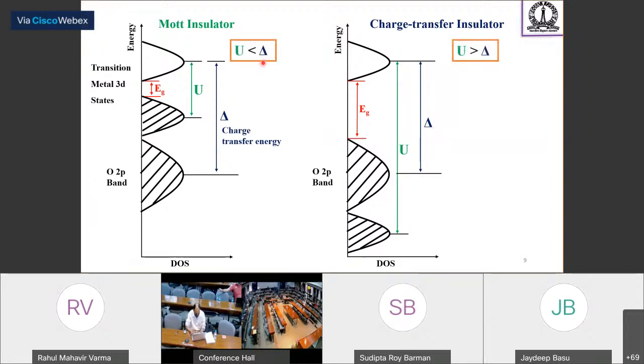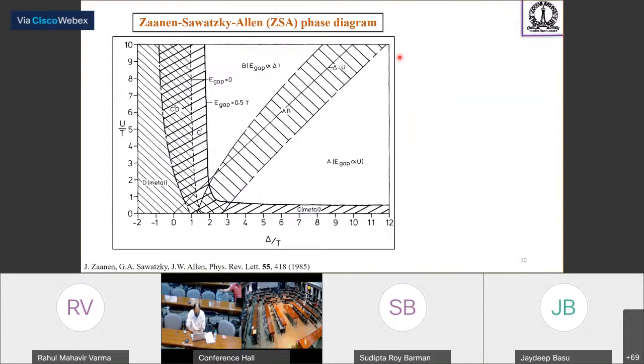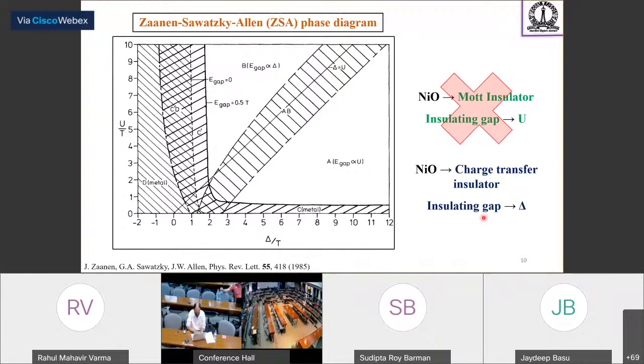If U is less than delta, then the system will be known as a Mott insulator. On the other hand, if delta is less than U, then the system is called a charge transfer insulator. So this finding resulted in a new classification of the transition metal oxides, which is known as the Zaanen-Sawatzky-Allen phase diagram. Before this, nickel oxide was thought to be a prototype Mott insulator, but after the introduction of charge transfer energy, Zaanen, Sawatzky, and Allen redefined nickel oxide as a charge transfer insulator.